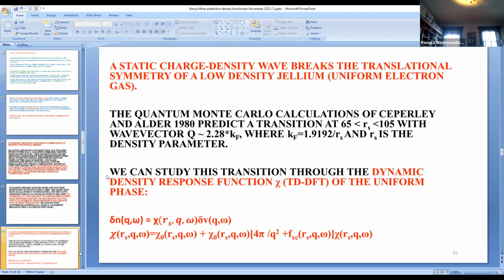And you can find chi of RS, Q, and omega from a Dyson equation, which is the last line on this slide. Chi zero is the Kohn-Sham or non-interacting response function, which is known. That's the Lindhard response function. And then we have another term where we have chi zero times an effective interaction between electrons times chi, the interacting chi. That effective interaction between electrons is 4 pi over q squared, the Fourier transform of the Coulomb repulsion between electrons.